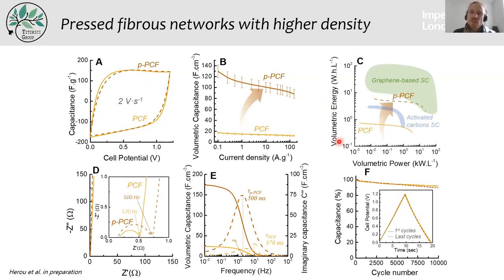And here, the volumetric energy versus volumetric power, where here we have the graphene-based supercapacitors, which are the last generations of supercaps, highly performing ones, and here the traditional activated carbon ones. And we can see that we outstand these materials by a little bit. And those are the cyclability results.